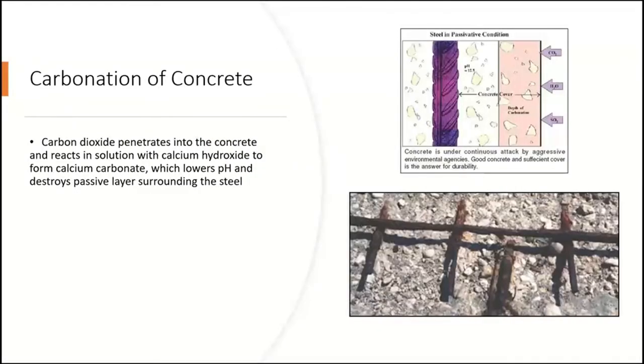The other effect that isn't talked about quite as much, but also contributes to the lowered pH of the concrete, eventually lowering it enough so that the passive protective layer around the steel is gone at some point, is carbonation. Atmospheric carbon dioxide and other things will create that chemical reaction and lower the pH of the concrete.